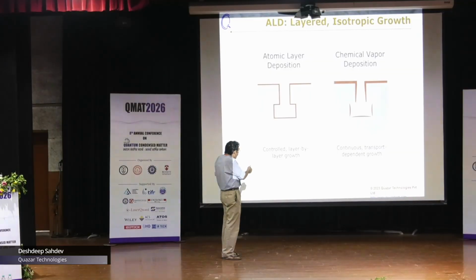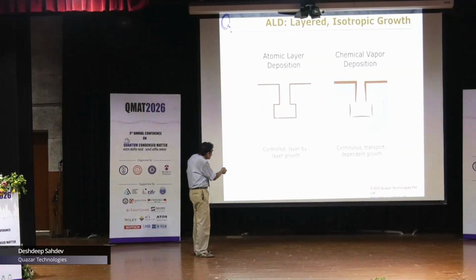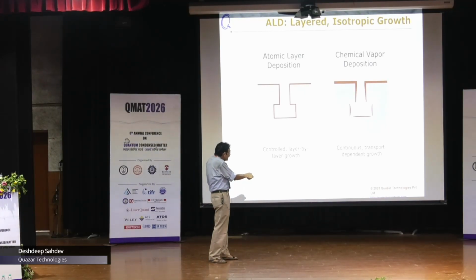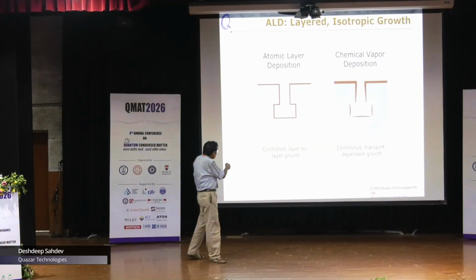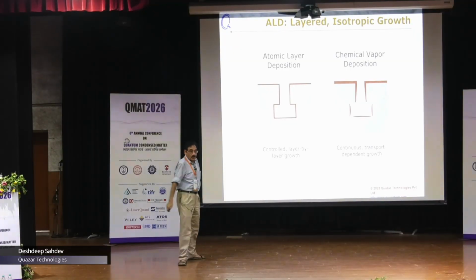And it's completely conformal, by which I mean that if you have a structure like this, it will coat it exactly, and the thickness will be uniform right through. This is what it'll be like for chemical vapor deposition. And if it's physical vapor deposition, it's just line of sight. You'll just get this much coated. These edges won't get coated at all, nor will these. It'll just be here, here, and here. But with ALD, you get completely conformal coatings.